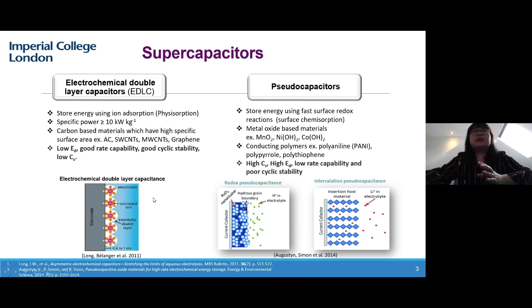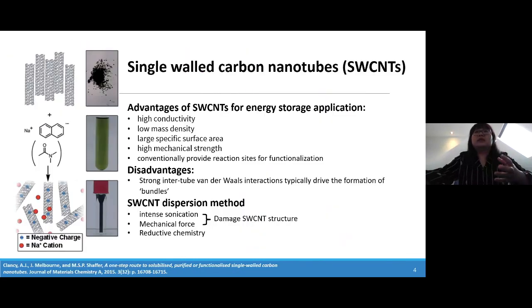But before going to that step, the first thing that we need to do is modify and optimize the electrode for the EDLC supercapacitor first. In that case, I use single-wall carbon nanotube materials as the electrode materials. The reason is that they have high conductivity, low mass density, large specific surface area, and high mechanical strength, which is suitable for both electrochemical and mechanical performance. And then, to further develop hybridized supercapacitors, they can easily give the functional sites to hybridize other pseudo-capacitive material on top of that surface.